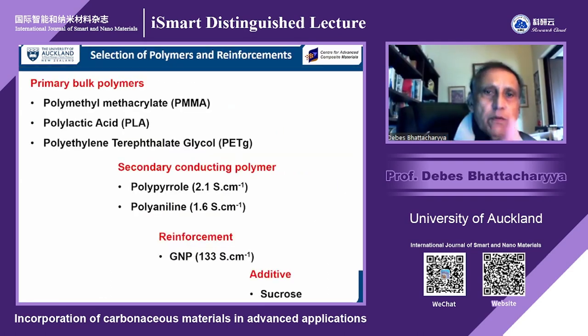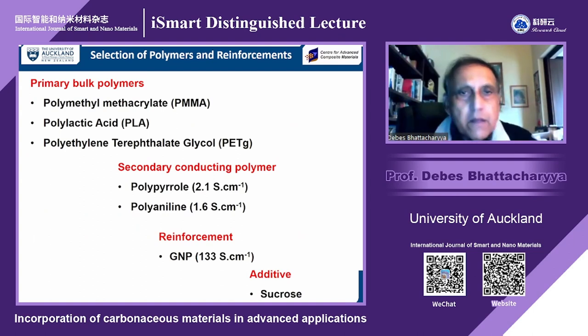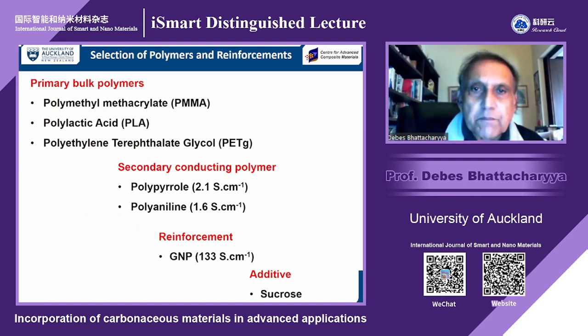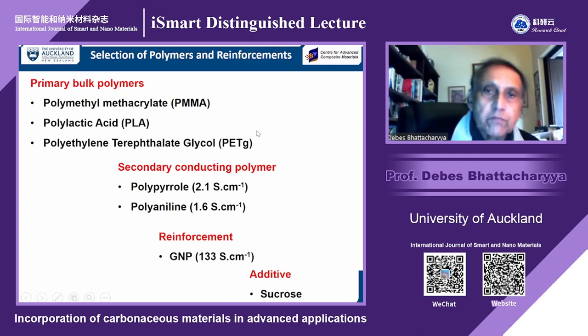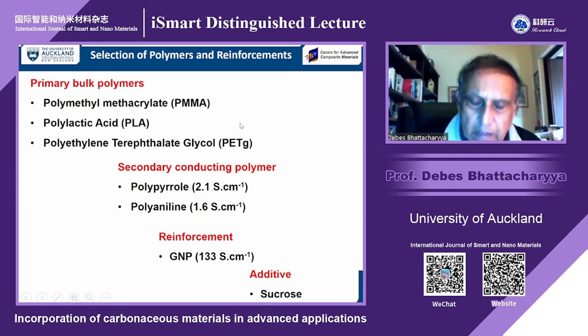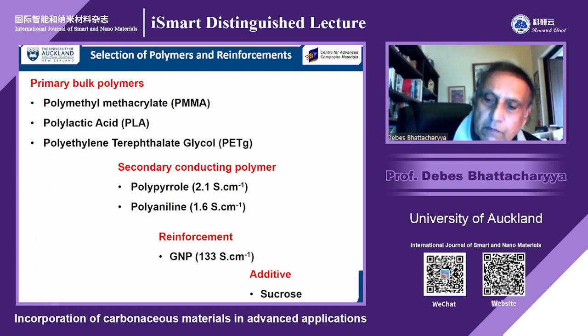So now we have got primary bulk polymers. You can see here we have deleted POM. We don't have that. We have PMMA. We have got PLA, biodegradable. And also we can have PETG, which is also bio, it is acceptable within the human system, this PET. And secondary for conducting polymer, same polypyrrole and polyaniline, reinforcement. This time we stuck to only GNP, didn't use RGO. And additive was sucrose, very small amount, about 1%.